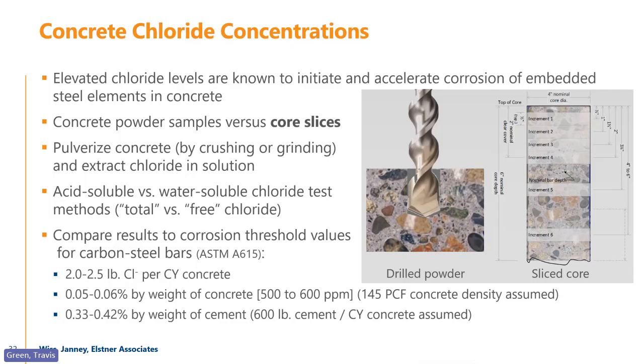We pulverize that concrete. There is a discussion about whether you use acid soluble or water soluble testing. I like acid soluble because that gets you everything, all the chlorides that are in that concrete. The challenge is, if you have bound chlorides within the aggregate particles, it also gets those because they're crushed, right? So generally speaking, acid soluble values are higher than water soluble values, and it just depends on the aggregates that you use about what that difference really looks like.